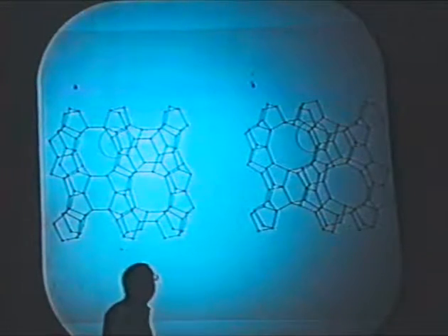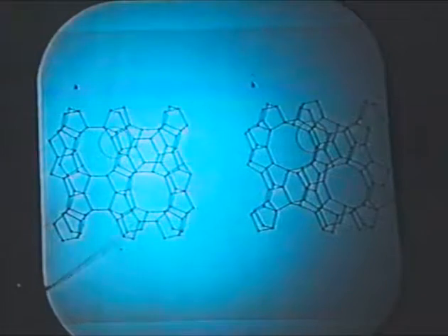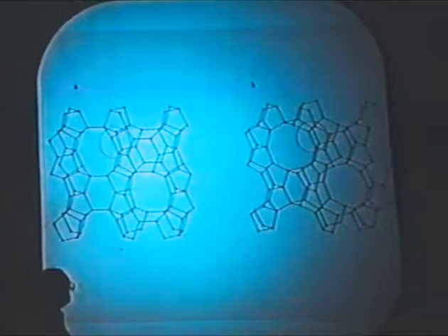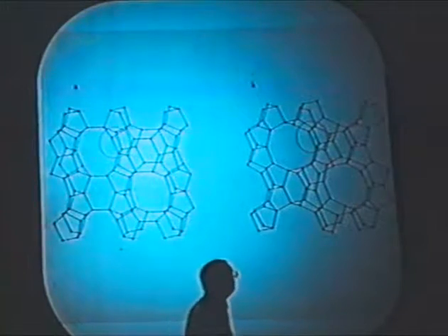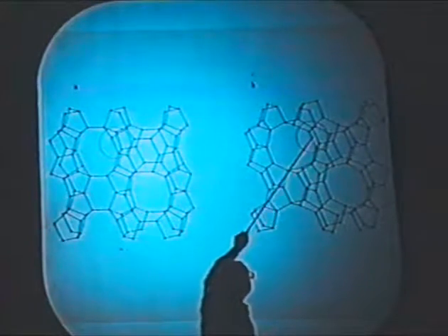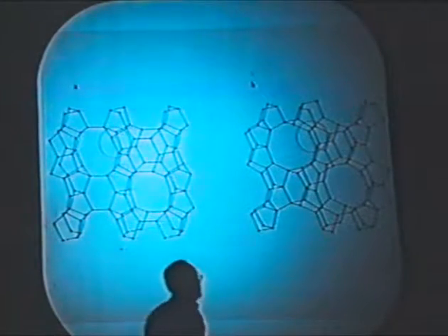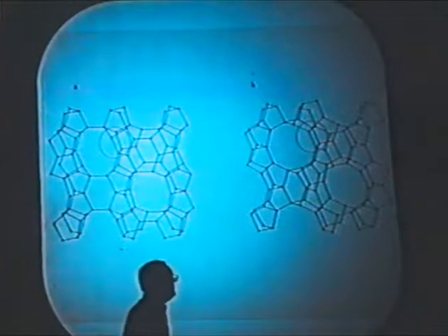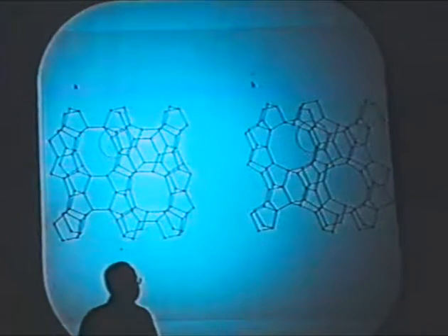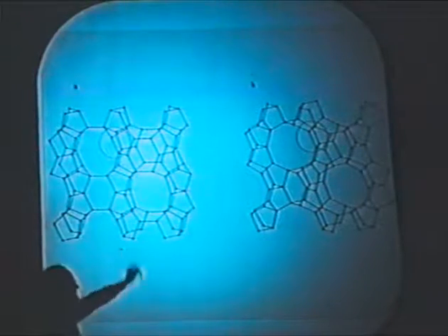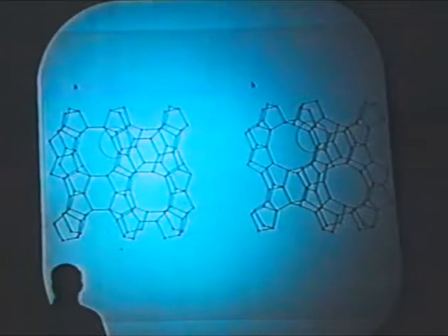The difference is that the ferrierite framework has 5 rings, 6 rings, 8 rings, and 10 rings. If you look where I've drawn the circle, you'll see a 5 ring. When you go to the corresponding position in the ZSM-57 structure, you'll see there's a 4 ring there. As a matter of fact, there are 2 4 rings side by side. So the framework topologies are different. The unit cells are essentially the same size, so all the lines fall in the same place. The different arrangement of atoms causes the intensities to change a lot.